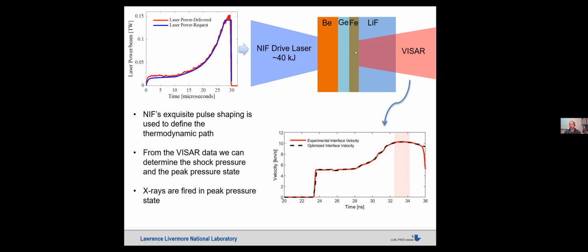And then the way that we diagnose those states is using a VISAR, a velocity interferometer system for any reflector, that measures the interface velocity between the lithium fluoride and the iron window. And because we know the equations of state and refractive index of LiF over such extreme conditions, as well as iron, our measurement of that interface velocity, where this is now velocity in kilometers per second and time in nanoseconds from 20 out to 36 nanoseconds.